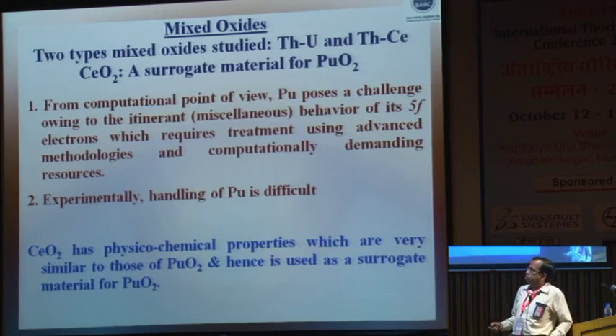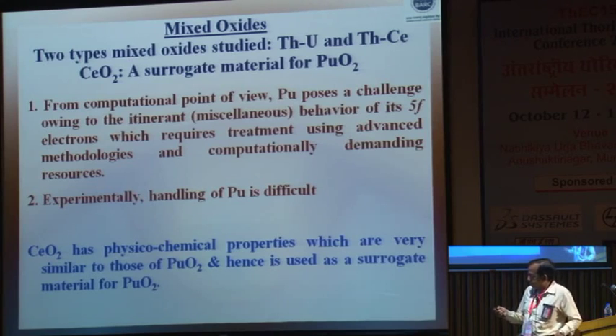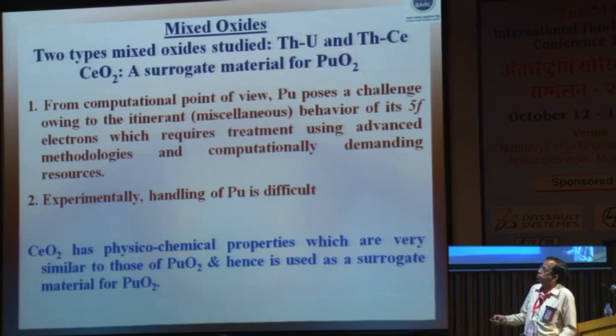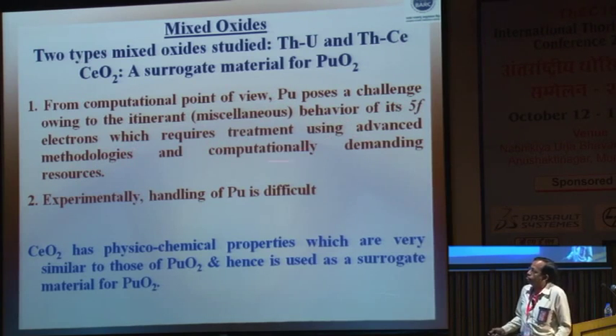So why mixed oxide? Well, of course, the advantages have been discussed at the beginning, but there are problems. Thorium uranium is not so difficult, but thorium plutonium is not so easy to study, both theoretically as well as experimentally. The reason for difficulty in theoretical studies, from a computational point of view, is that plutonium poses a challenge owing to the itinerant behavior of its 5f electrons, which requires treatment using advanced methodologies and computationally demanding resources. This is the problem to deal with plutonium theoretically.